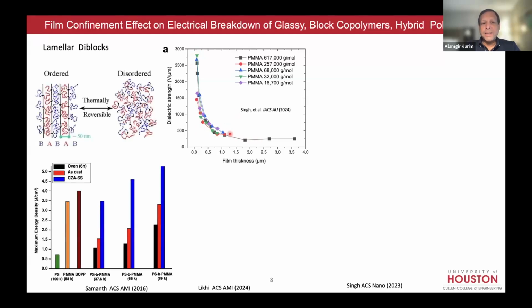And we have shown that for polystyrene and one or two other polymers. It doesn't work well with rubbery polymers, for reasons I explained earlier. But let's take another example, block copolymers. These are polystyrene-PMMA lamellar-forming diblocks. When you cast them from a solvent, like flow coating or spin coating, they are in a disordered state because the solvent rapidly evaporates and vitrifies the disordered state of the block copolymer, and you get energy storage like 3 joules per cc, as you can see here, in the disordered state.